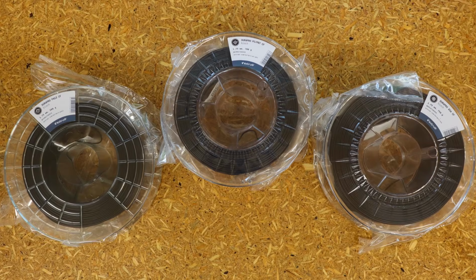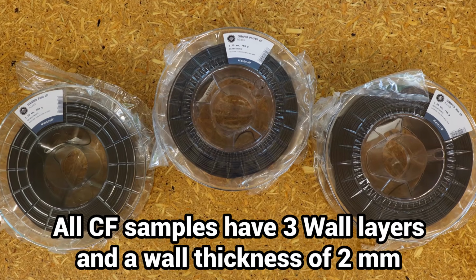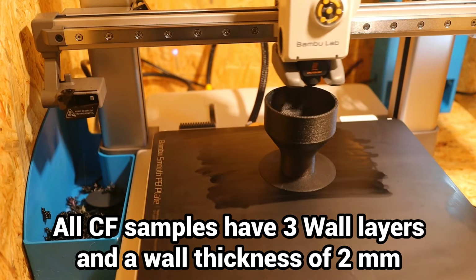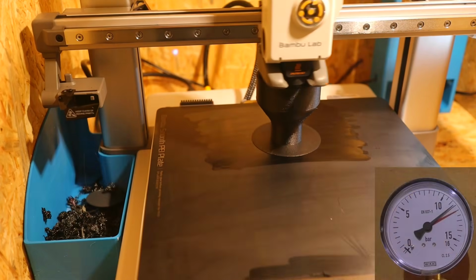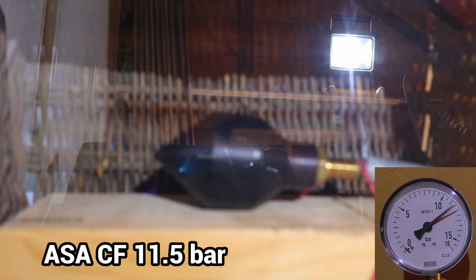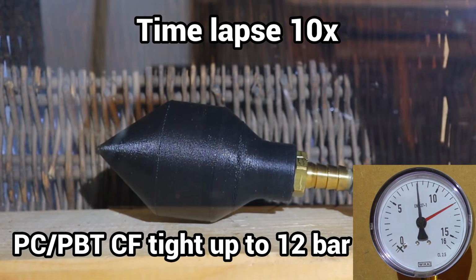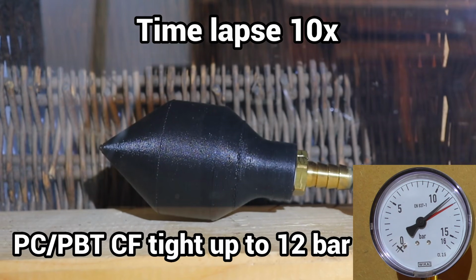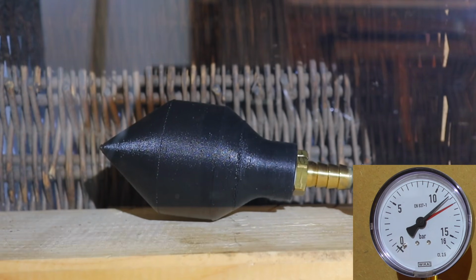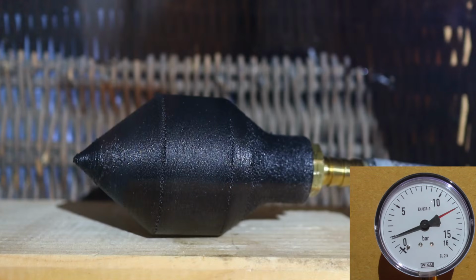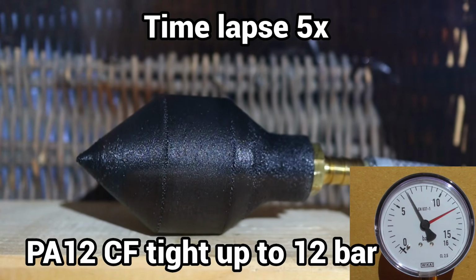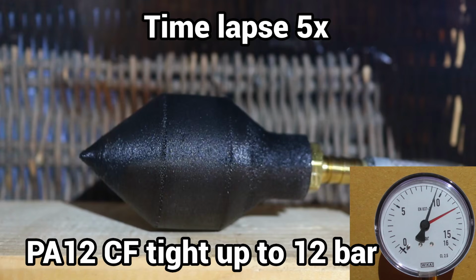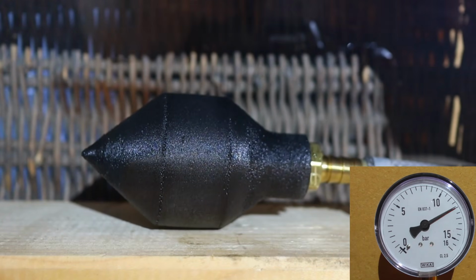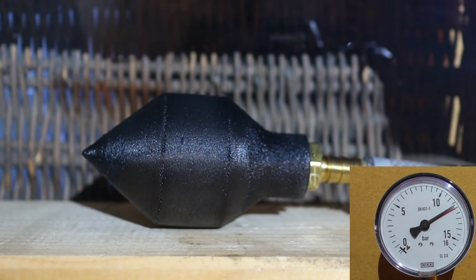Now it's time for the carbon fiber reinforced engineering filaments with 3 wall layers and a material thickness of 2 mm. ASA-CF exploded cleanly between the layers at 11.5 bar. PCPBT-CF remains completely leak-proof up to a maximum pressure of 12 bar. PA12CF can also withstand overpressure of up to 12 bar without problems. Unfortunately, I'm unable to achieve pressures higher than 12 bar, which would give even more meaningful results.